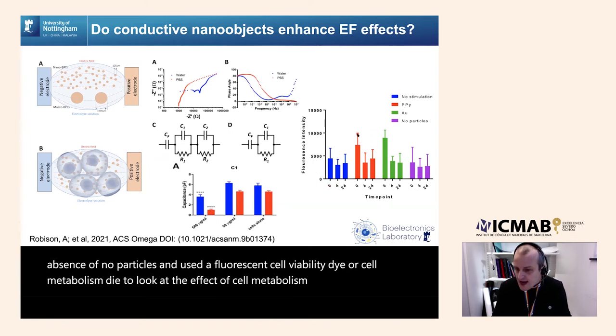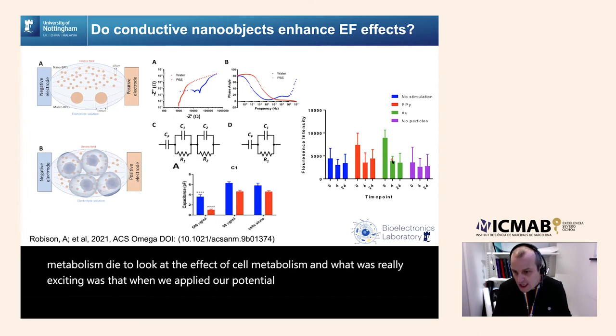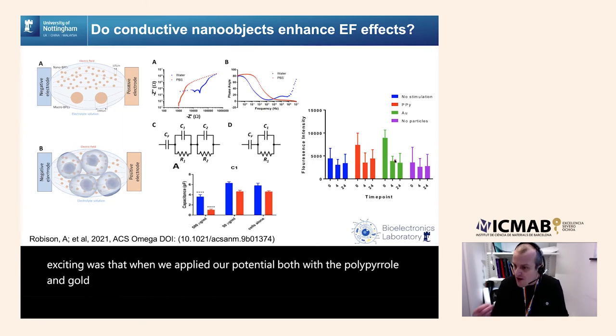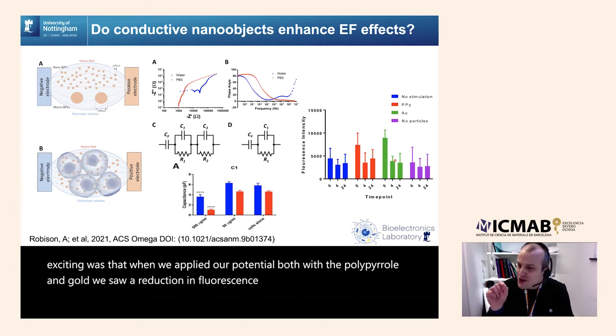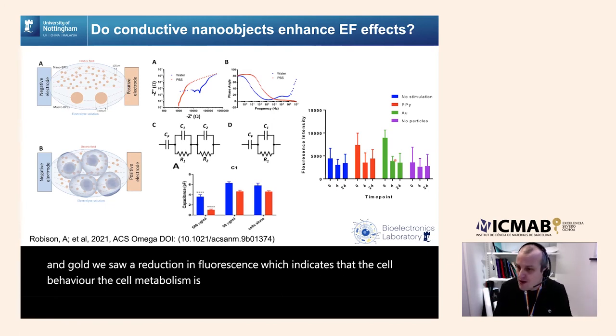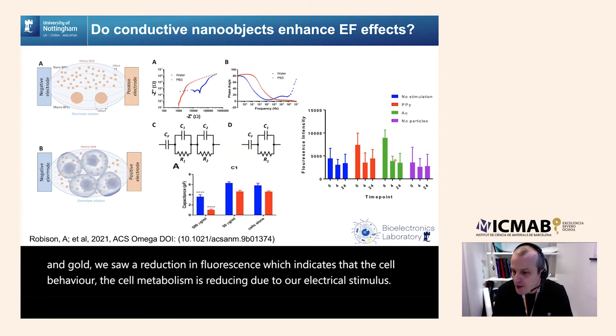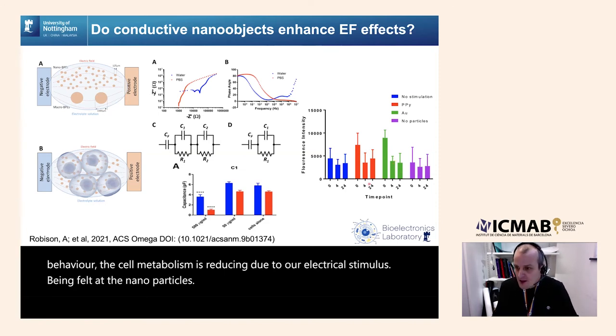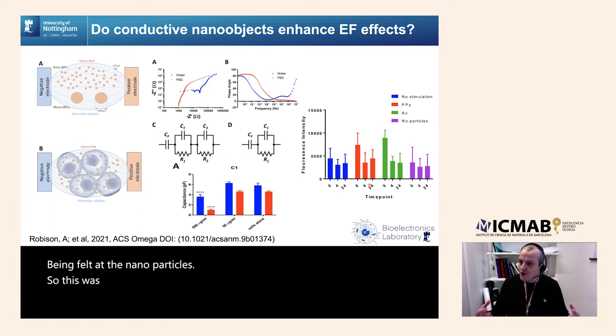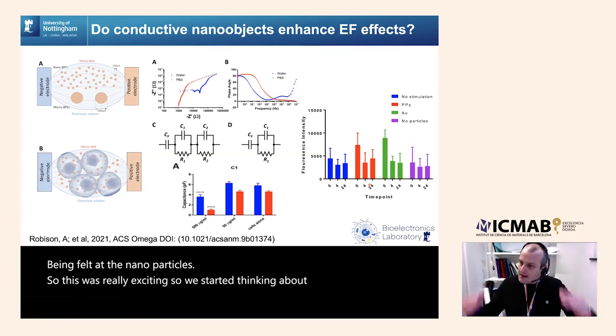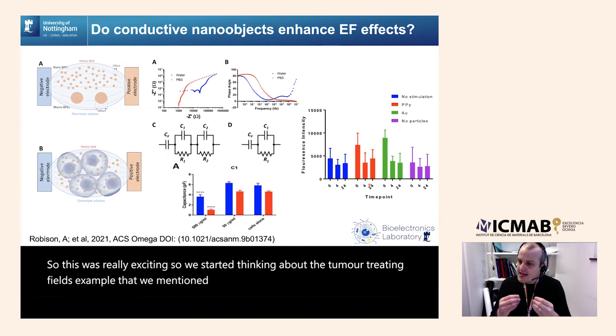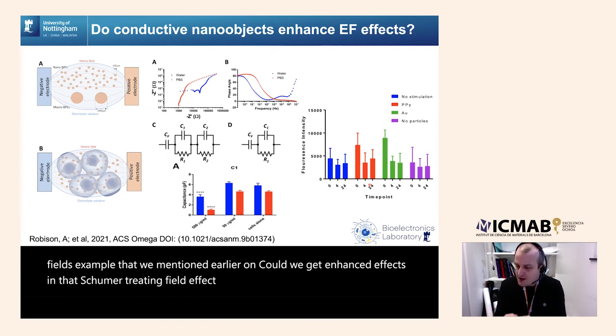And what was really exciting was that when we applied our potential, both with the polypyrrole and gold, we saw a reduction in fluorescence, which indicates that the cell behavior, the cell metabolism, is reducing due to our electrical stimulus being felt at the nanoparticles. So this was really exciting. So we started thinking about the tumor treating field example that we mentioned earlier on. Could we get enhanced effects in that tumor treating field effect by localizing the electric fields using these conductive nano antennae?